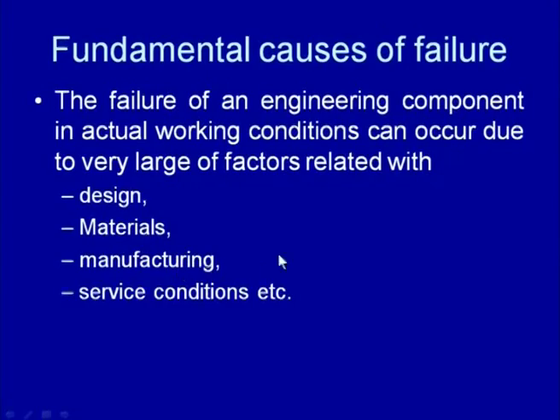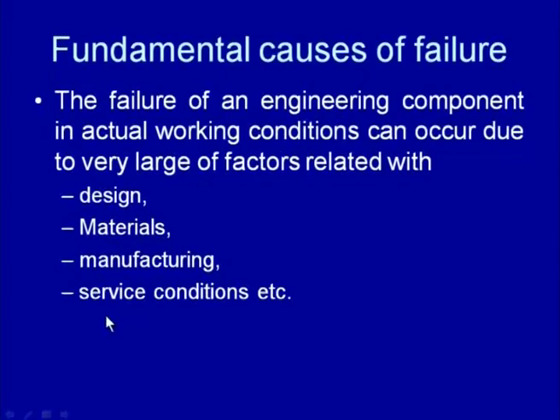So, there can be various situations where manufacturing-related process parameters can introduce discontinuities in the weld joints and the component which is being manufactured, and that can be the source of the failure of the component. And the service conditions also vary, ranging from very steady load to fluctuating loads, at room temperature, then low temperature to very high temperature conditions, under very normal environmental conditions to very severe corrosive or saline environmental conditions.